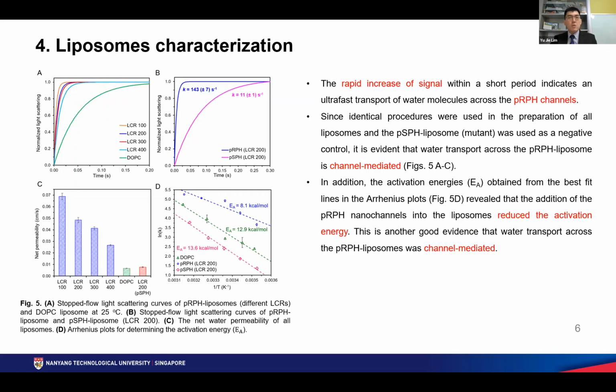In addition, we also conducted the activation energy measurements by performing the stopped-flow light scattering test at different temperatures. From the Arrhenius plot in figure 5d, it was revealed that the incorporation of PRPH into liposomes reduced the activation energy needed for water permeation from approximately 13.6 kilocalorie per mole to 8.1 kilocalorie per mole. This is another good evidence that water transport across the PRPH liposomes was indeed channel mediated.